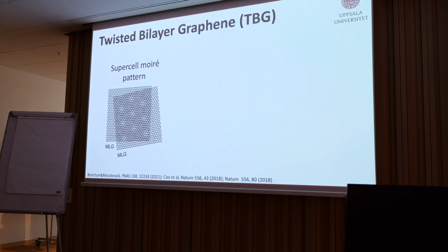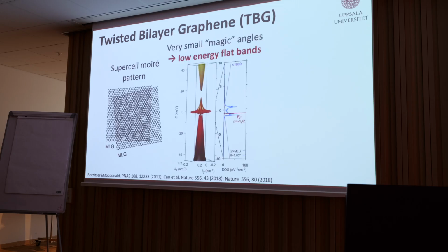Okay, so we already heard this morning about twisted bilayer graphene, so I'll go pretty quickly through here. If you take 2 layers of monolayer graphene and twist them by a certain angle, you get this really nice Moiré pattern. What is really interesting is that at certain small angles, you get very flat energy bands. The band structure completely flattens out. This is trying to illustrate that, sitting at this magic angle, you get a very flat structure here with very distinct peaks in the density of states.